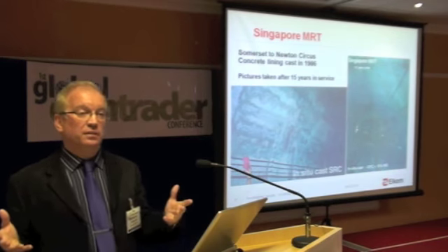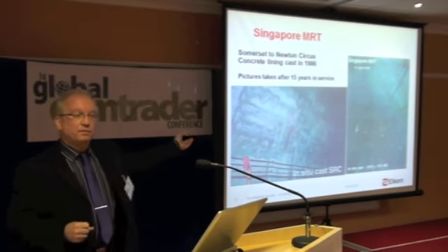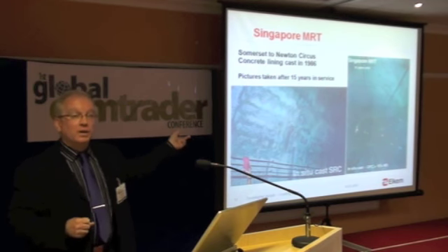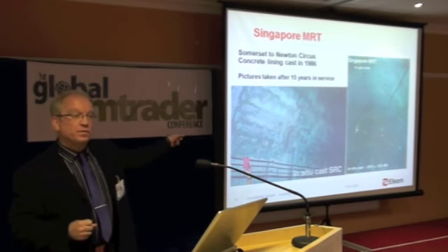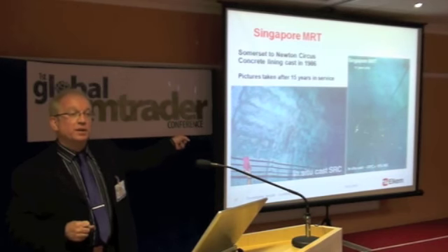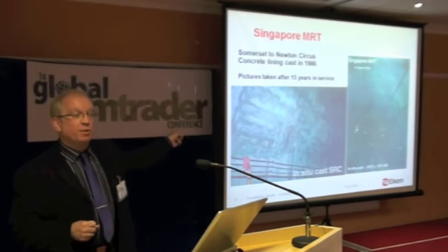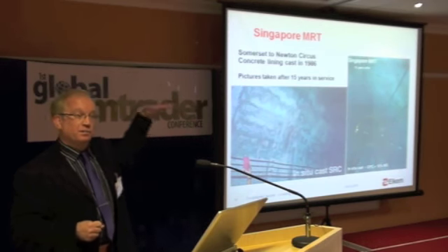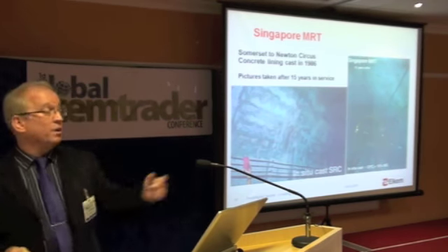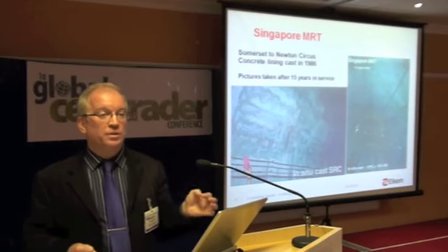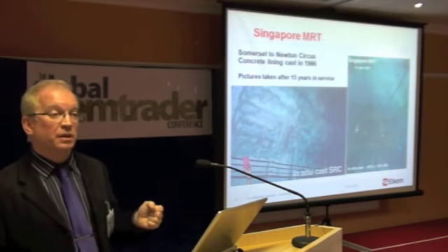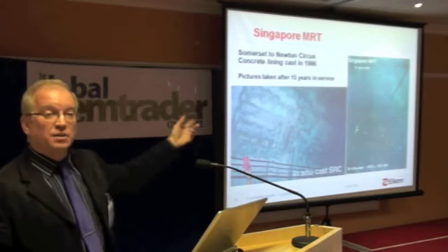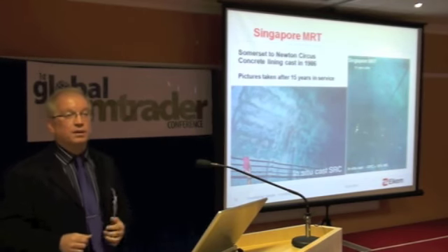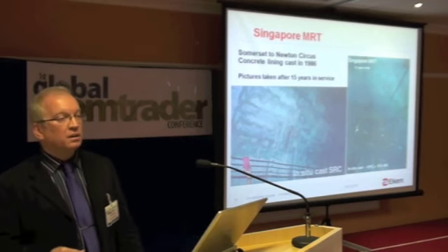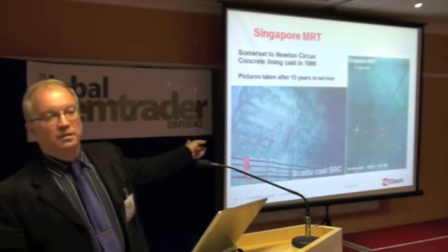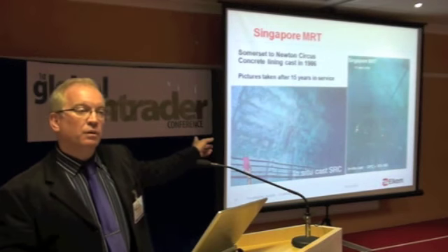The reason is it's not really that great at sulfate resistance. It slows it down. But 15 years in the sulfate-rich soil in Singapore has destroyed this concrete. That's a 400 cement content SRC mix with a membrane to protect it from the ground outside. The other one is a 400 cement content with 10% as part of that cement content of microsilica, in this case silica fume, same thing. And you can see that it looks a bit dirty, but it certainly doesn't have the sulfate attack that this side does.